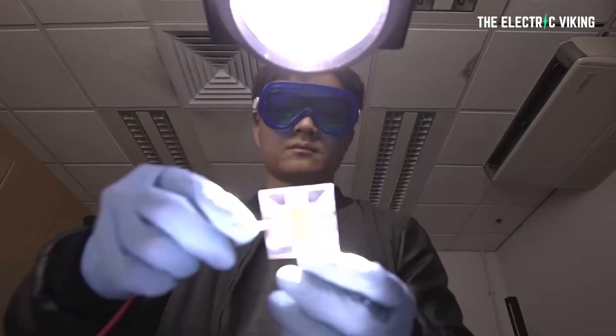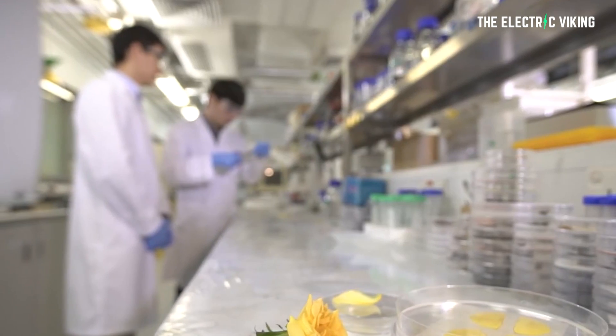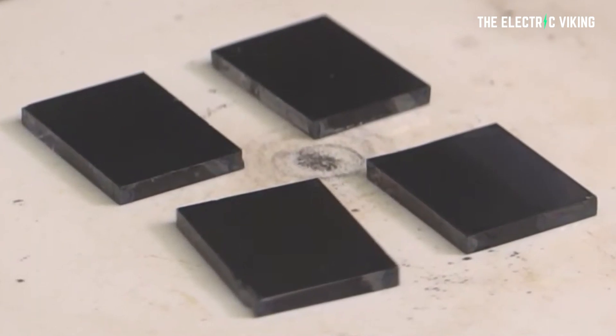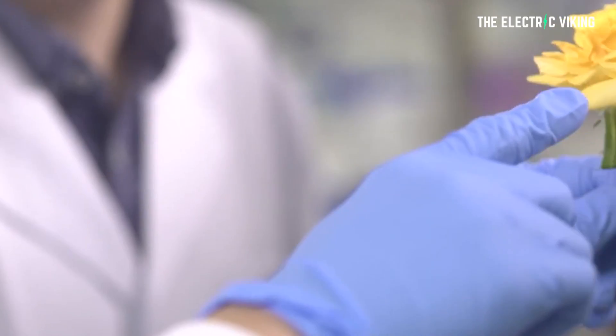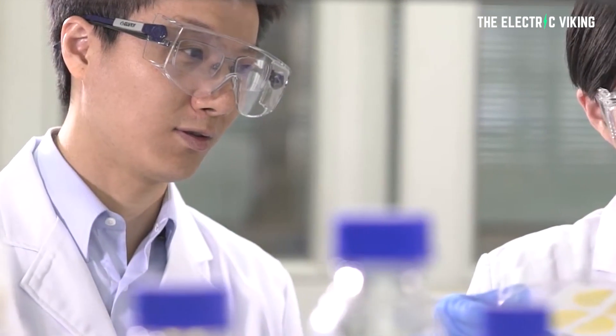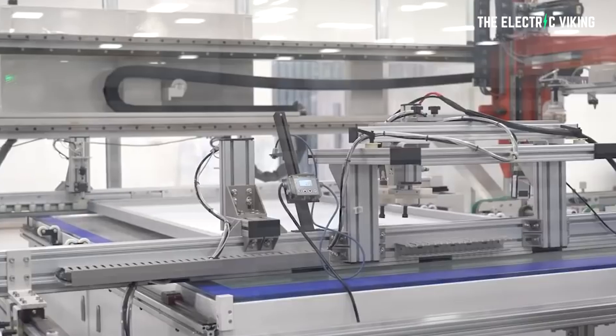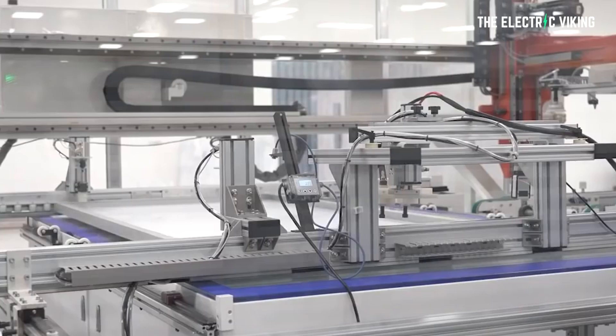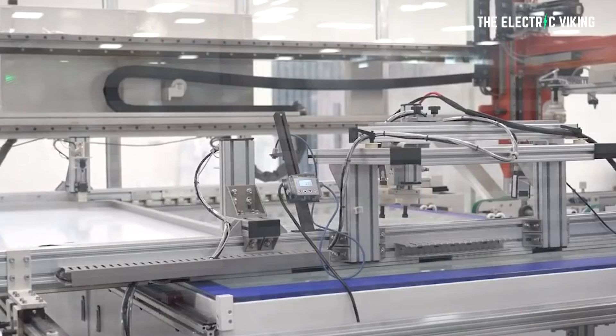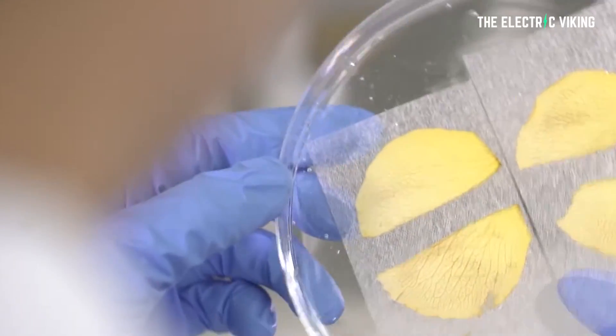Researchers from the Netherlands and Belgium successfully improved the efficiency of the semi-transparent cells up to 19.7% with an area of 3×3 mm². The result has been independently certified by the European Solar Test Installation Lab in Italy. The silicon device, optically stacked under the perovskite, contributes an efficiency of 10.4% to the total solar energy conversion. Combined, the conversion efficiency of the researchers' non-area-matched 4T tandem device reached 30.1% — a new record.